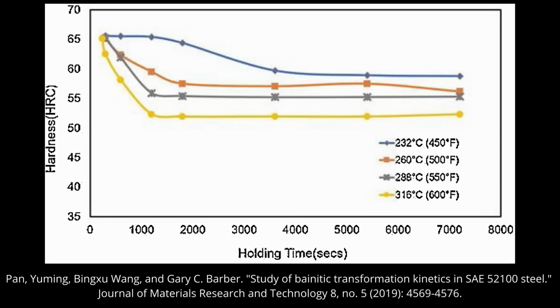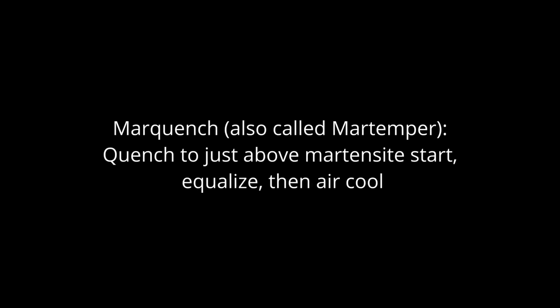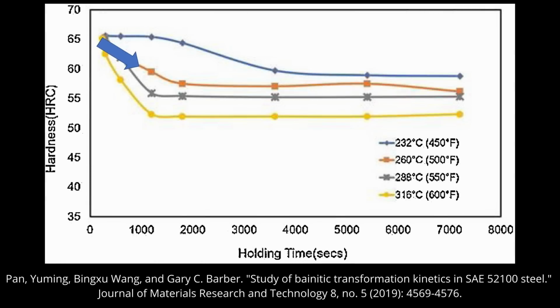It's called a mar quench, and I'm going to show some results for hardness and toughness on O1 when it is mar quenched. That just means we quenched to an intermediate temperature and equalized so the steel part was all the same temperature before then letting it air cool to form martensite. And the properties can be a little bit different, even when you do that, not forming any bainite. But you can see that the hardness is dropping as more and more bainite formed.